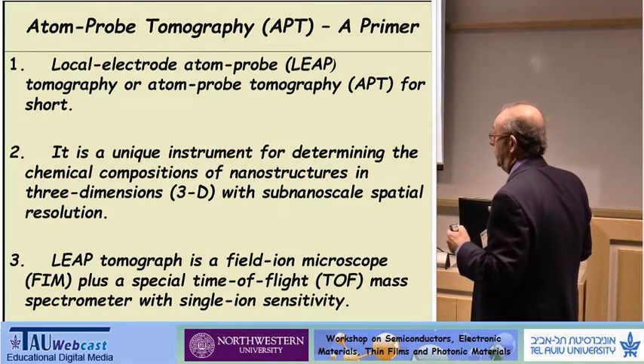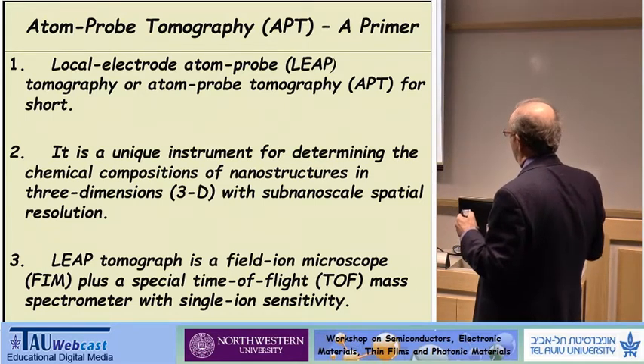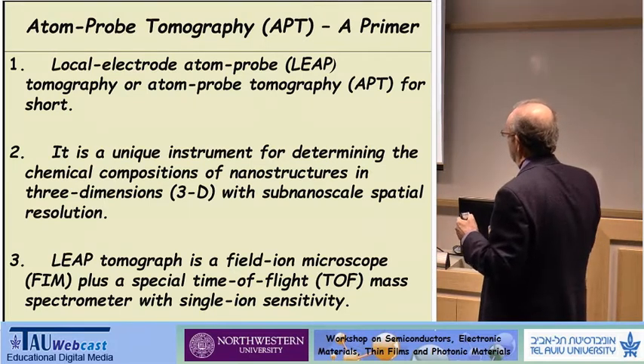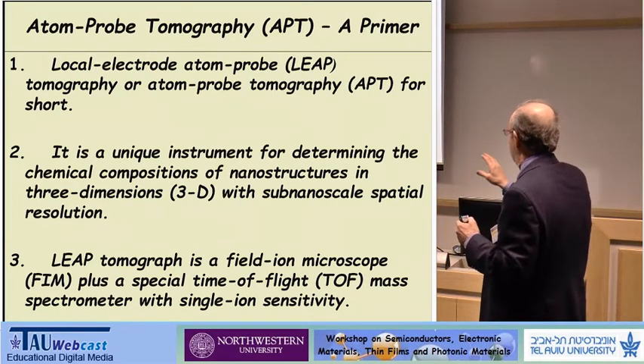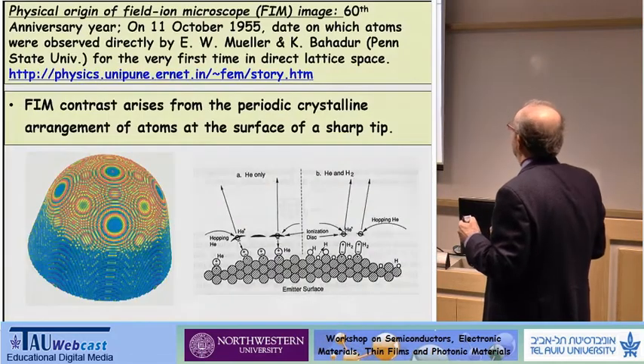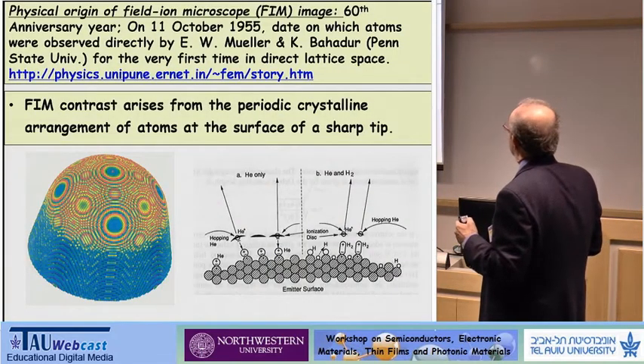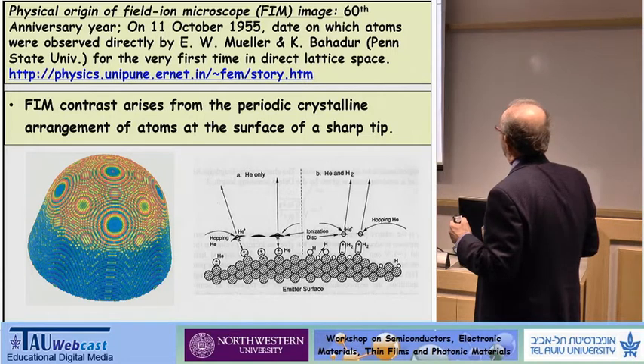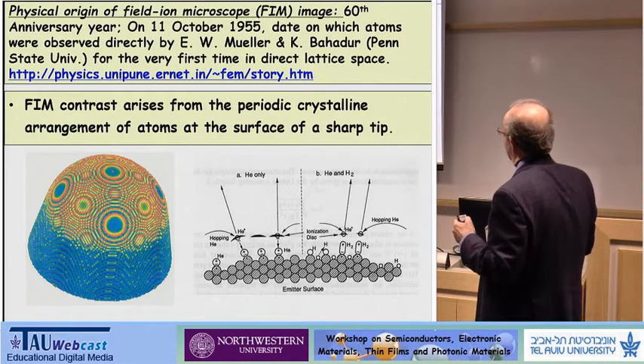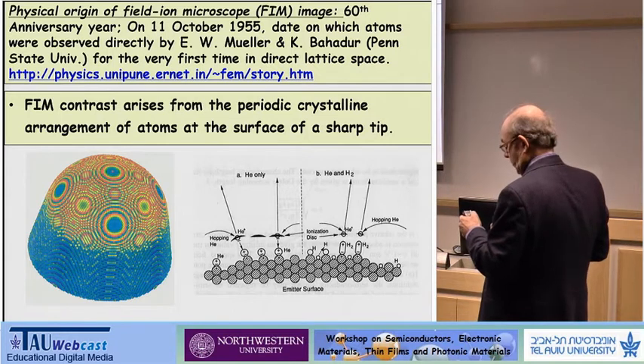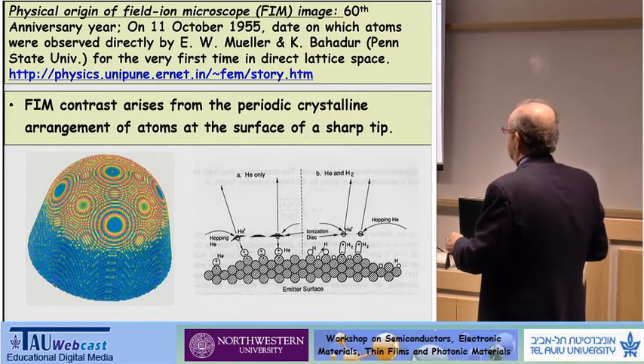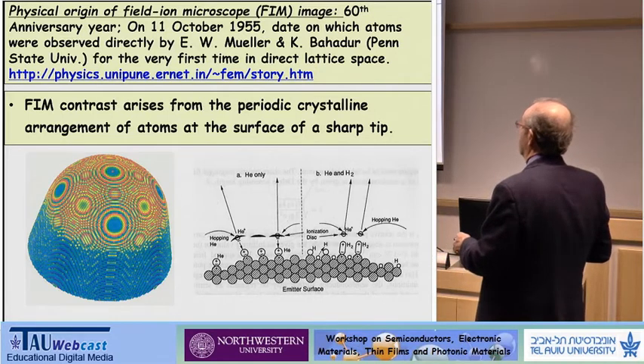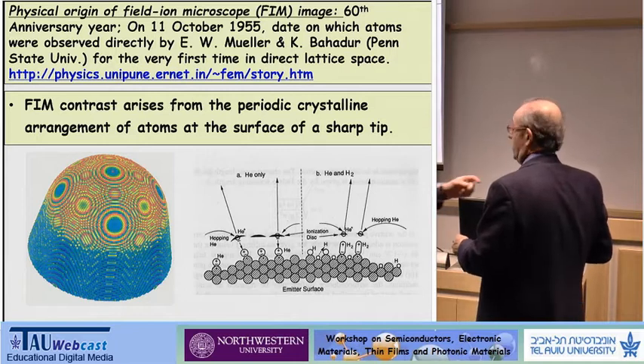And it's a unique instrument because you can map out the positions of atoms in three-dimensional space, in direct lattice space, and you can determine the chemical identity of each atom that you detect. And it has single ion sensitivity, this mass spectrometer. The original instrument, the field ion microscope, dates back to 1955, the first observations of atoms on the surface of a specimen. And this is a simulation of a specimen, and basically it's a curved surface, and you can see individual atoms.